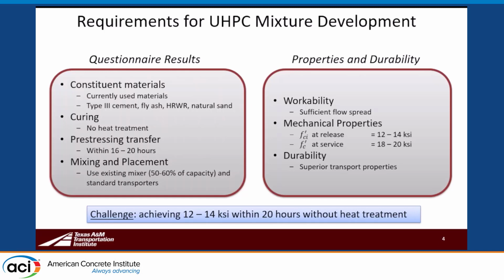And then natural sand. So in starting out in our laboratory mixes, we did start out doing some sieving of the sand. We did some oven drying, but when we got to the plant, we soon realized that that is not going to be possible, and so we had to look at the use of natural sand as it comes from the pile at the plant. Curing was another issue that we asked about, and because the producers in Texas really don't need to use heat treatment, they preferred not to have a situation where they're required to use heat treatment. And so we looked at trying to do this without heat treatment.